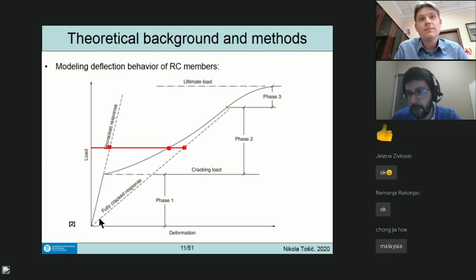And if the entire beam was fully cracked, so only composed of the compressed concrete and the tensile reinforcement, you will have this kind of response. But of course, you're never going to have a fully cracked section, because you're always going to have something in between the cracks. You always reach that maximum, that state of developed crack state where you cannot open new cracks.